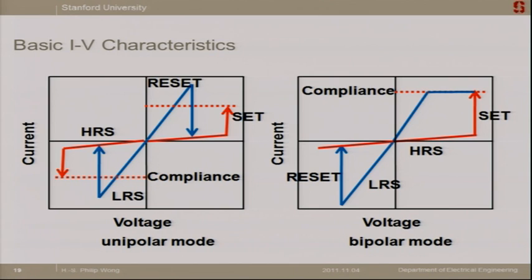And if you don't limit the current by some kind of compliance, either in your measurement system or by a transistor in series with it, then you will actually blow up the device, and you basically have a hard breakdown and you have a short. But if you do limit it to the soft breakdown, then the device will switch into a low resistance state, like this blue curve here. If you want to go back to the high resistance state, you go to a negative voltage and you will go back to this state. This is the bipolar mode.